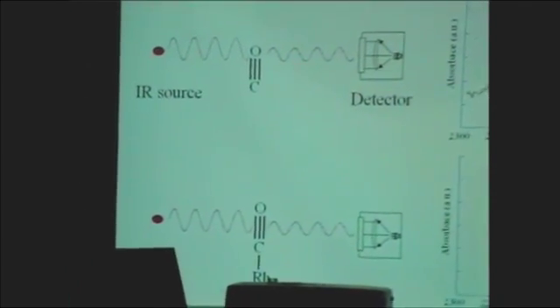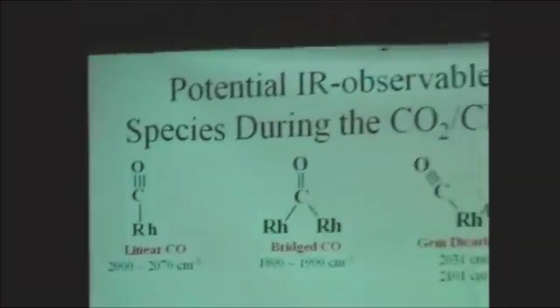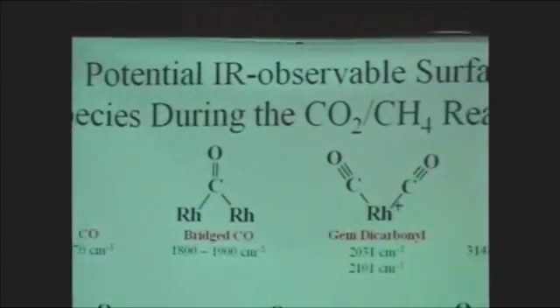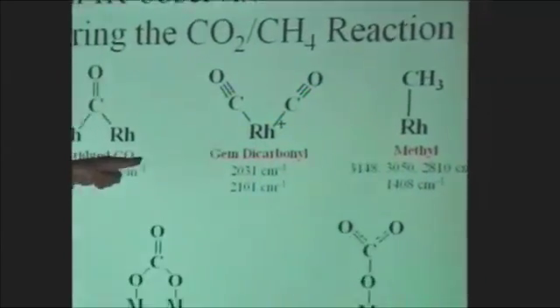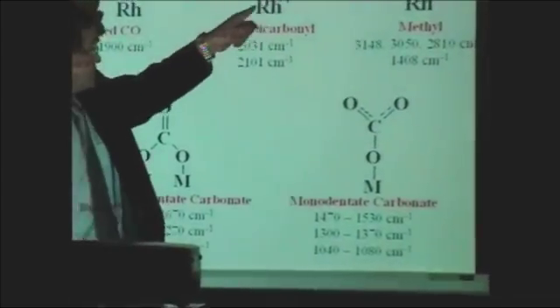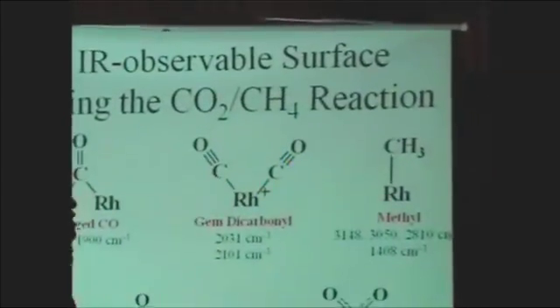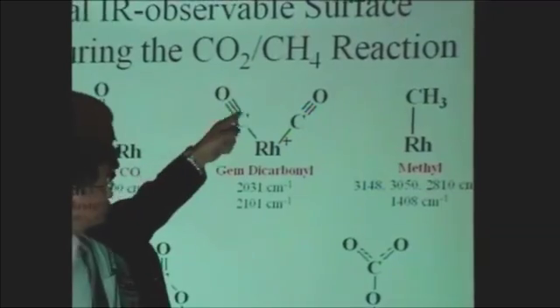So infrared is a very good tool here to study how the reactant adsorbs on the catalytic surface and to characterize the catalytic surface. Especially for CO adsorption on rhodium, it is a very good tool. I just want to quickly point it out here. The CO can adsorb on the rhodium surface in linear form, bridge form, and gem-dicarbonyl form. If the rhodium is in the oxidized state, then you will adsorb the CO in the gem-dicarbonyl